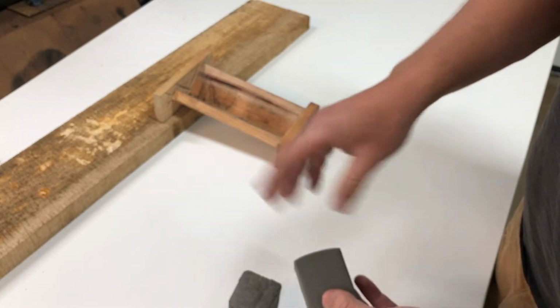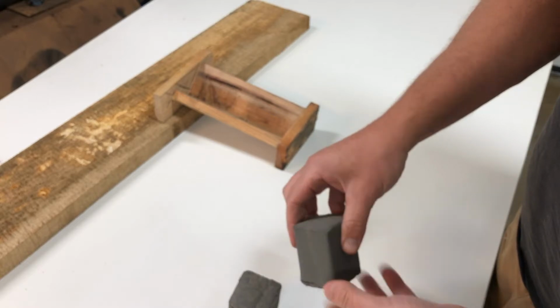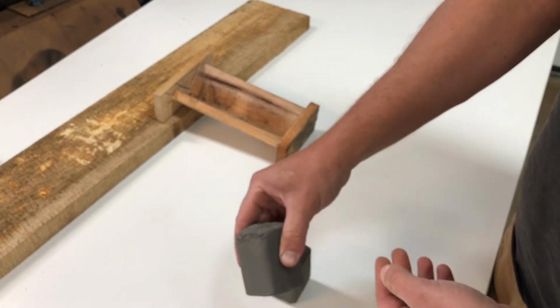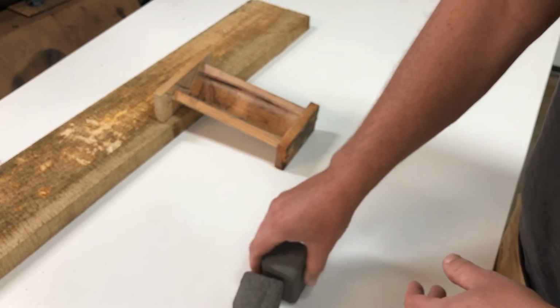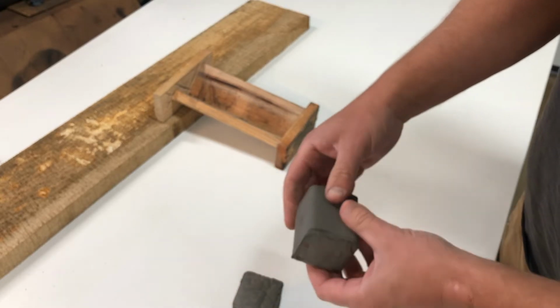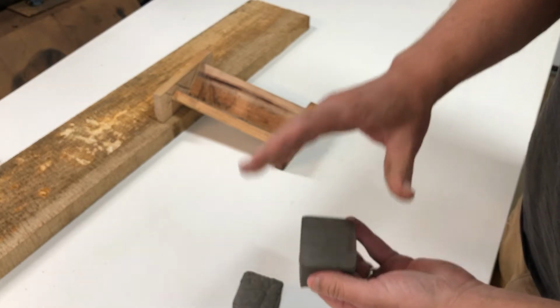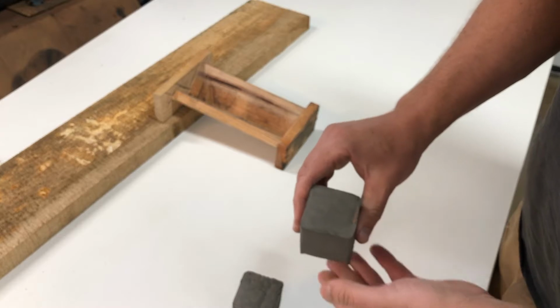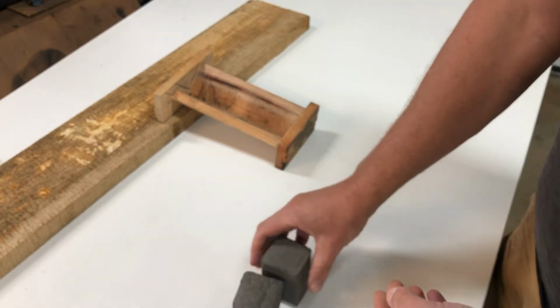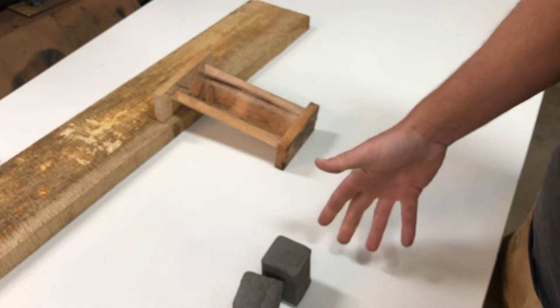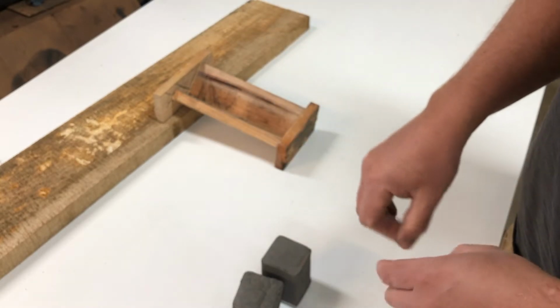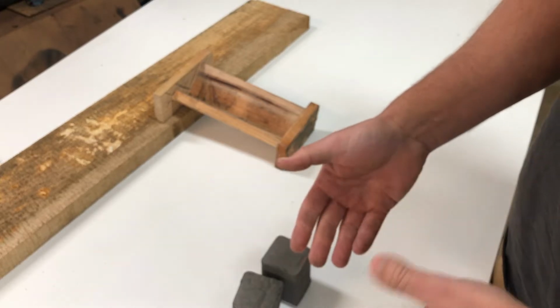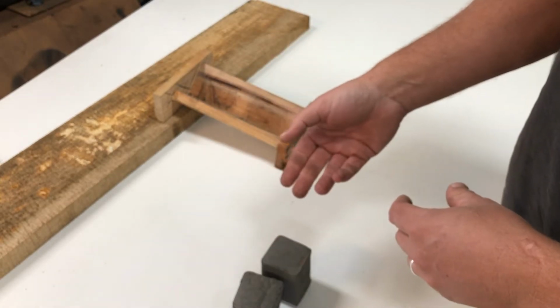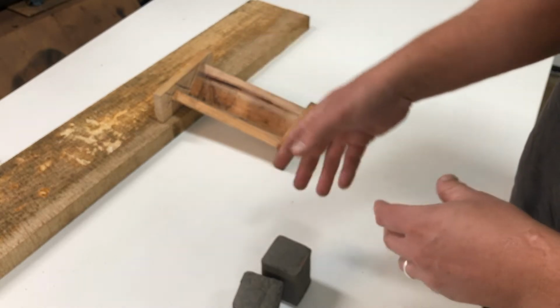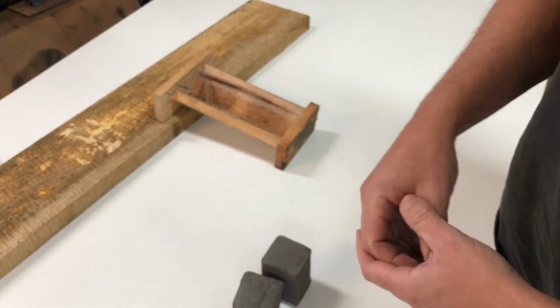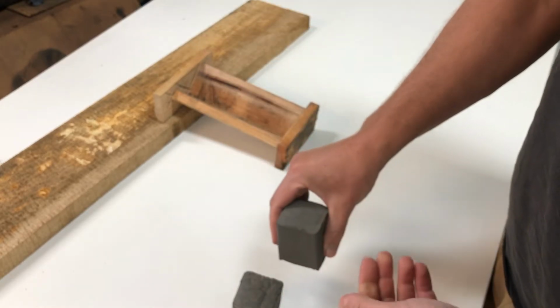Kind of the two key temperatures are somewhere around 150 degrees Fahrenheit, and then again the 212 degrees Fahrenheit boiling temperature. The 150 degree temperature is a little sensitive just because around that temperature the methyl cellulose actually goes out of solution. So you could have a lot of moisture come out very quickly. So what we want to do is dry the water out, slowly evaporate it, rather than boil it out or have it juice out, so to speak.